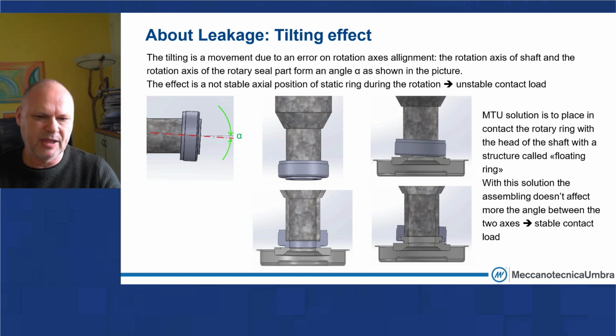So when a rotary part of the mechanical seal is assembled on the shaft, the mistake between the rotation axis of shaft and the rotation axis of rotary part could form an angle. This angle produces a tilting effect. This tilting effect increases the leakage. We developed a solution in this product to avoid that this mistake during the assembling affects the leakage rate.